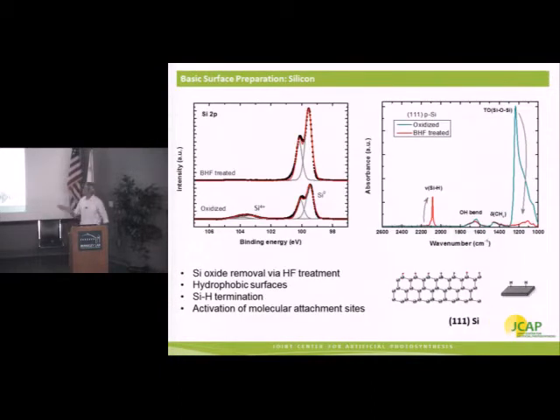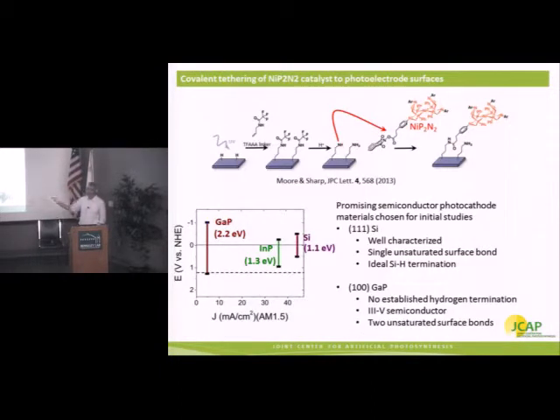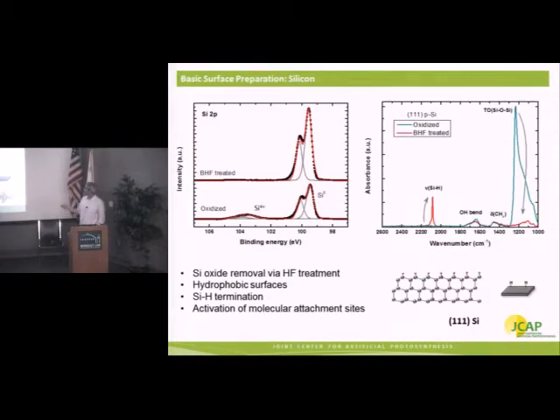The synthetic procedure we use is outlined here. We first create a reactive semiconductor substrate, in this case on silicon with hydrogen terminal sites. Using a UV photoactivated process, we can bind an alkene linker molecule onto that surface that's protected on its end group. We deprotect it and link that to a catalyst that has an anchoring group tethered to it, ultimately resulting in a covalently grafted molecular catalyst on a semiconductor surface. I won't belabor the point here. We are able to develop very well-defined surfaces.